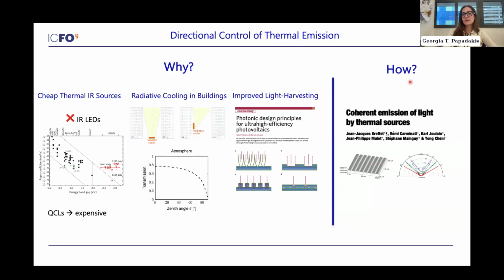Now, how can you do this? Of course, the simplest way to do it is to mimic what Jean-Jacques Greffet did in 2002 in this Nature paper, where, as I said before, he built these nice gratings, and building these gratings allows the propagated surface phonon polaritons in silicon carbide, one of the best materials for mid-IR photonics, to diffract in different diffraction orders that you can see here with these very narrow lobes.